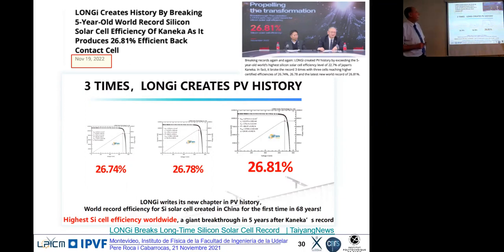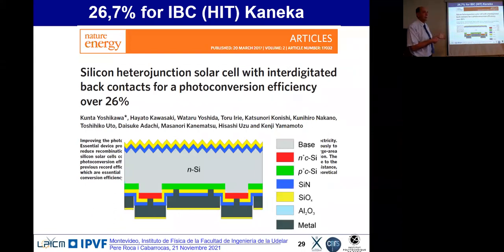There's no extra price, and in fact, the game from aluminum back surface field to this has been to simplify the process. This one was started by SunPower in the United States, they were using lithography. It's insane. It will never work in industry. But then engineers came up and found solutions to get rid of lithography. First, these contacts are interdigitated, and the distance, this space, should be of the order of the diffusion length of carriers in the crystalline silicon, hundreds of microns. Without lithography.